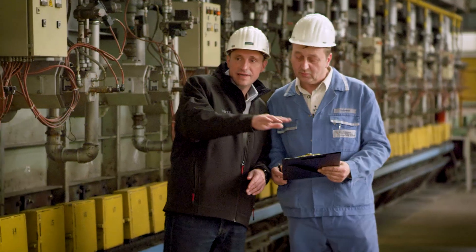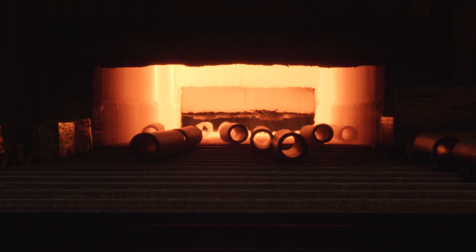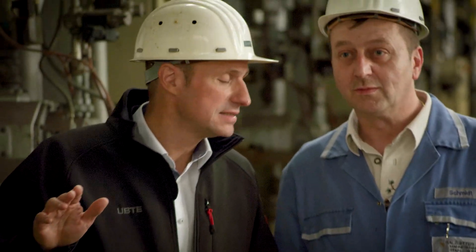This fact is already proven with our customers. The dry rolls of S&C fulfill the special requirements of high temperature applications and at the same time have a high service life and rigidity. The challenges for dry rolls in our furnace are varying temperature ranges from 560 to 1,230 degrees Celsius. In this environment, the 60HTR material of Schmidt & Clemens has proven itself particularly well. In 2006, we performed a test phase together with Schmidt & Clemens for furnace rolls made of the 60HTR material. These furnace rolls have been in use for up to nine years in some cases. Based on the experience we gained in this test, we installed 10 additional furnace rolls in the high temperature zone of up to 1,230 degrees Celsius in 2012.